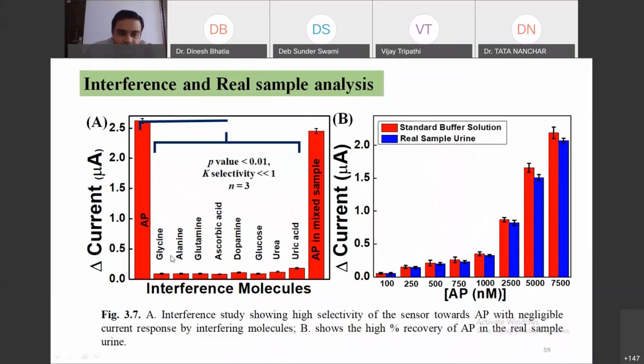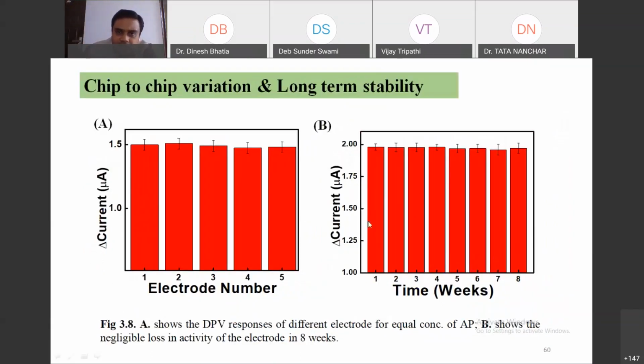So this is the interference of closely related molecules which coexist in the system, and this is the mixed sample analysis. It means we have added all these molecules together with the target molecule, and you can see it is almost similar to when we tested it separately. This is with the standard condition data, and this is the real sample analysis where we have tested the urine samples. So this is the chip to chip variation, and this is the long term stability. It means when we incorporate such materials in the chip, there is a very minor variation, and the shelf life is quite high. It is about 2 months. That is very important from a commercial perspective, right?